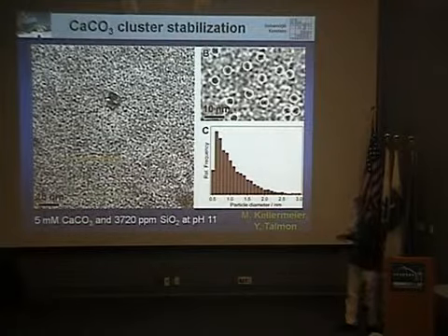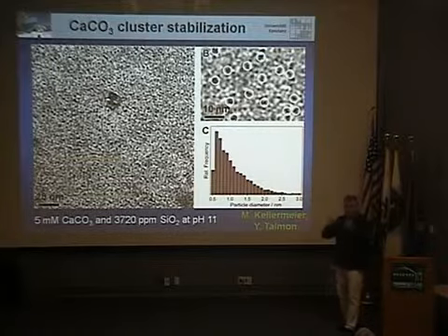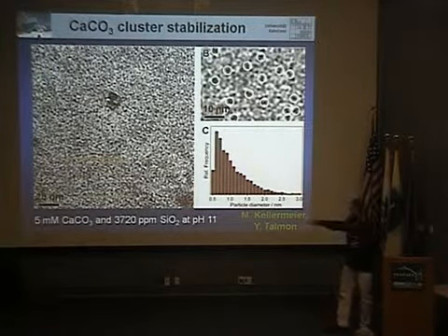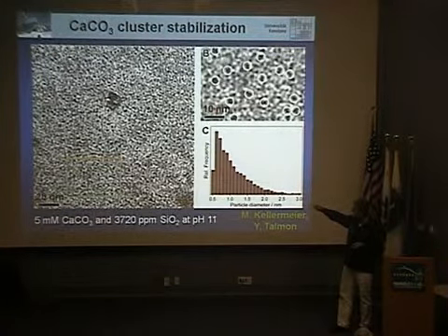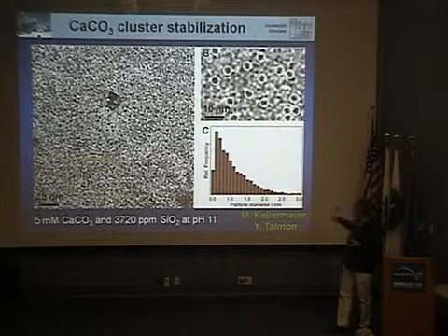And Matthias Kellermeier from the University of Konstanz did some experiments by precipitating these clusters in presence of silica. And finally, what he ended up with was clusters which are coated by a silica shell. And you see high-resolution TEM here, and you see the clusters all over the space. So if you zoom in here, the rectangular thing, you see the clusters are there. They are pretty defined in size.